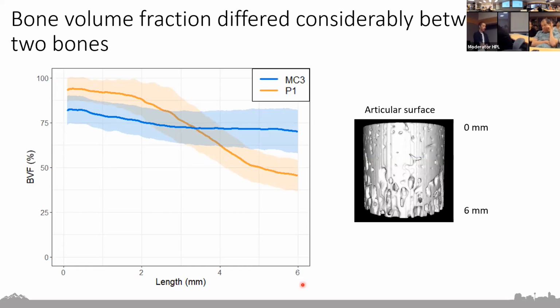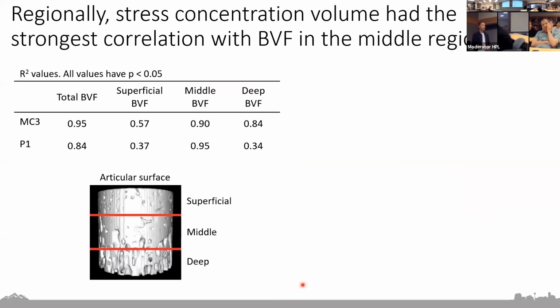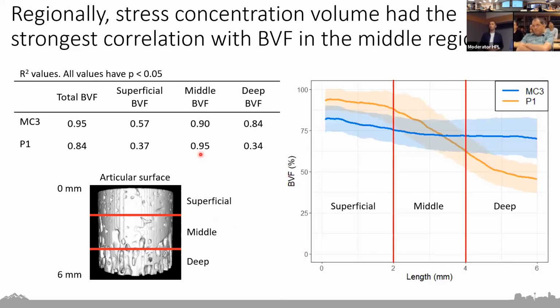So we dug into this bone volume fraction a little bit more and conducted this regional analysis where we split our bone samples up into a superficial, middle, and deep region. And we found stress concentration volume had the strongest correlation with bone volume fraction in the middle region. And that was particularly true for the P1 bone at a super high R-squared value. And then looking back at that plot of bone volume fraction, we see this middle region, especially for the P1, that's where we saw a lot of that variation in bone volume fraction.